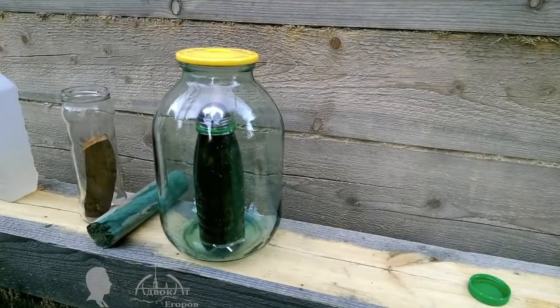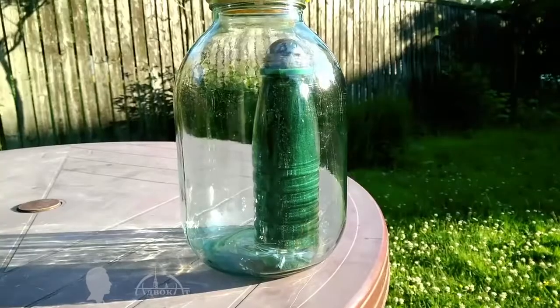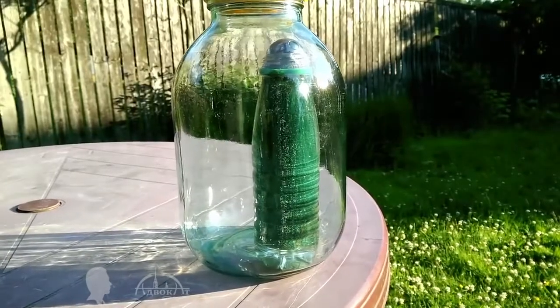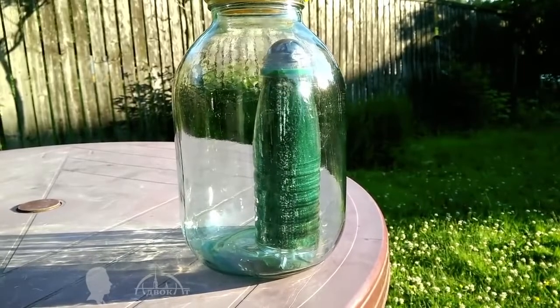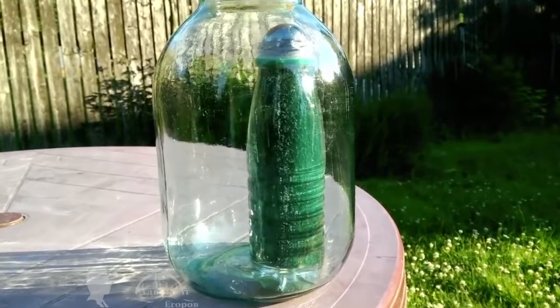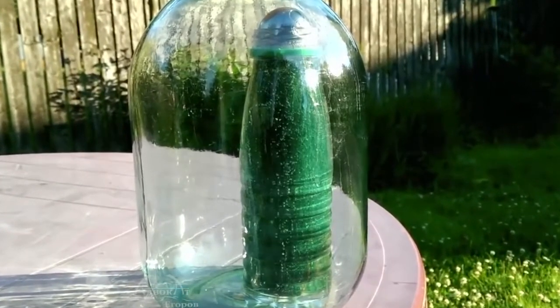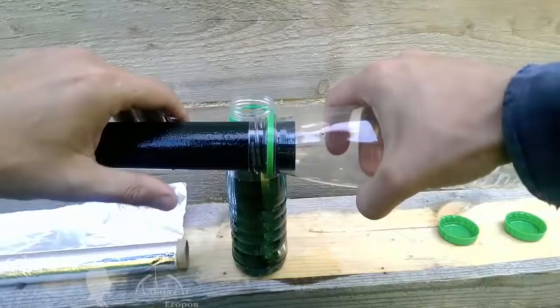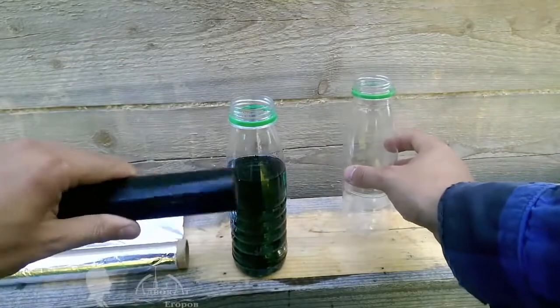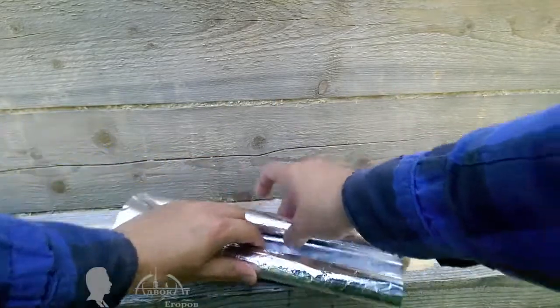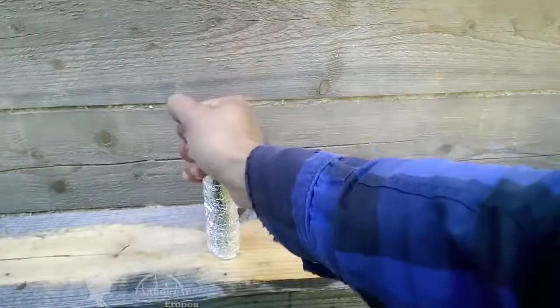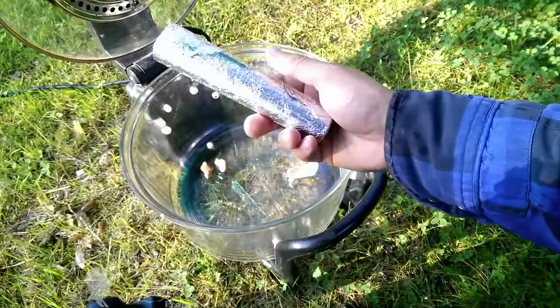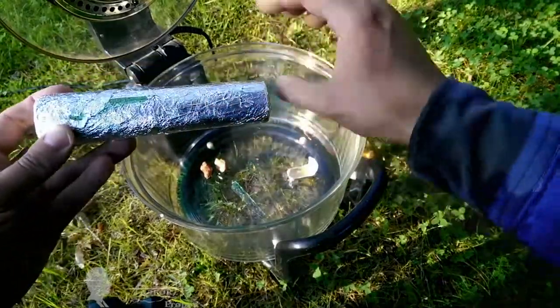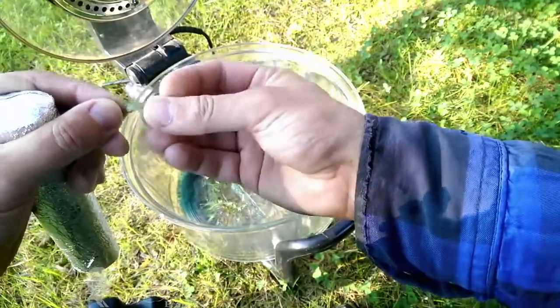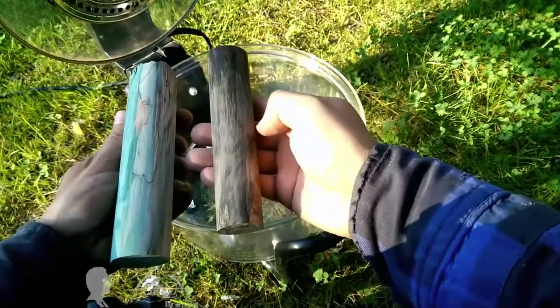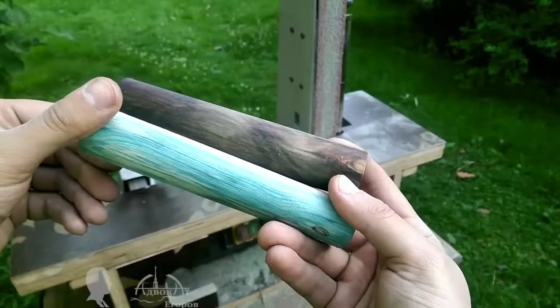While applying vacuum and squeezing out air bubbles from the blank's pores, the rotted wood barely consumes the polymer. However, once the pressure in the vacuum chamber is normalized, the blank sucks the Anacrol in like a sponge, replacing air in its pores with liquid polymer. The Anacrol impregnated blank changed its color and became 2 to 3 times heavier by feel. To polymerize this thermosetting resin, I wrapped the workpiece in foil and heated it up to 90 degrees Celsius, 200 Fahrenheit. The fact that Anacrol polymerizes only in higher temperatures is very convenient. However, it can also change the wood's color, which is a downside in some cases.